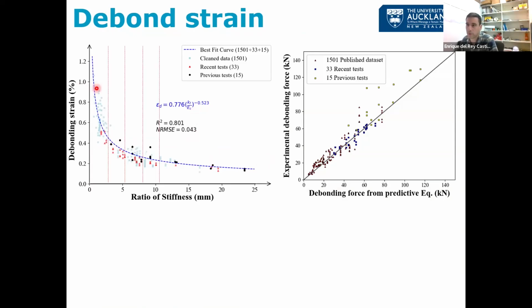So just to give you a rough idea, I've put these 4 lines there. This is 1, 2, 3, and 4 layers of the typical product, the Sika that we all know, but they are all the same, Simpson or 5, they are all similar products in terms of strength and weight. So we can see that with 1 layer, we get about 0.4, but then it drops very rapidly. If we are using 4 layers, it drops to about 0.2% strain.